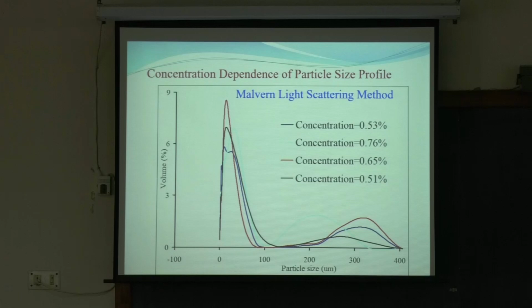One had more than 100. If you have that more than 100, then the volume percent of surface area will come down almost so low. But if you have the fly ash around 10 to 15, the other three, then the volume of surface area will become much higher. All right? And if you have much more surface area, that means this stress transfer will be much more. Then this fly ash has much higher strength than polymer. Then the polymer will transfer this stress to the fly ash, and the fly ash will take it over. All right?